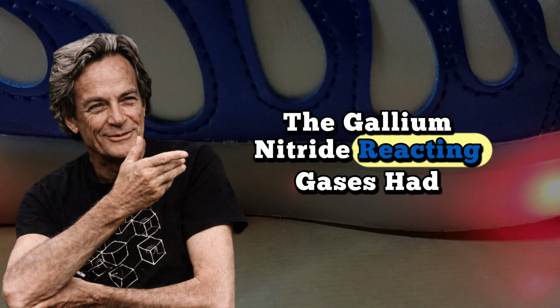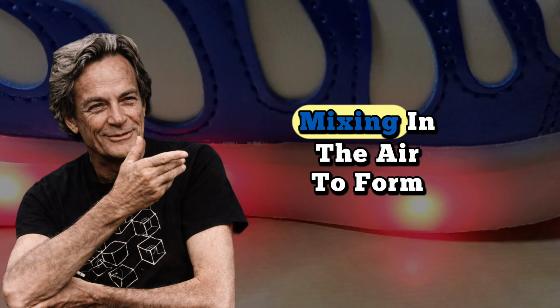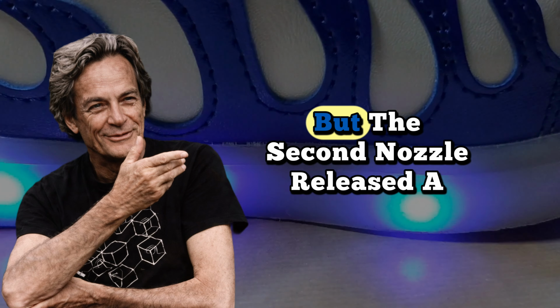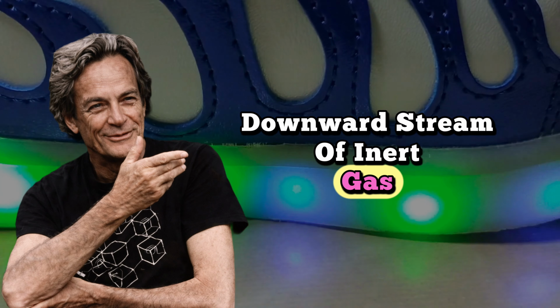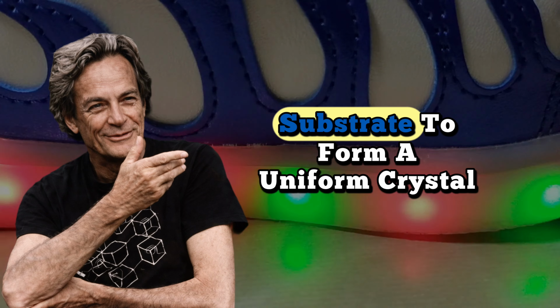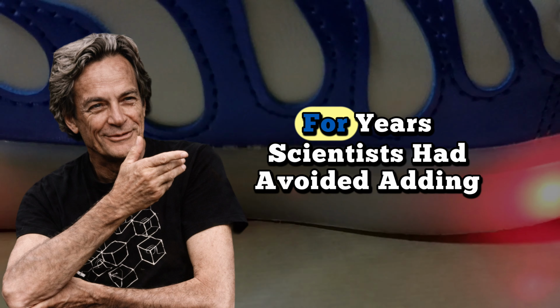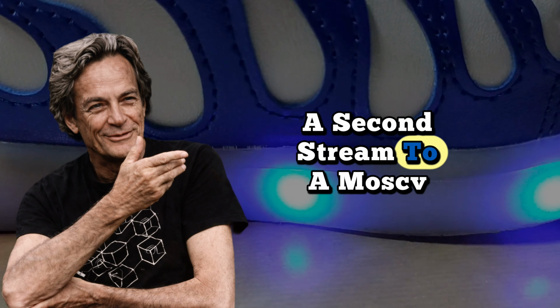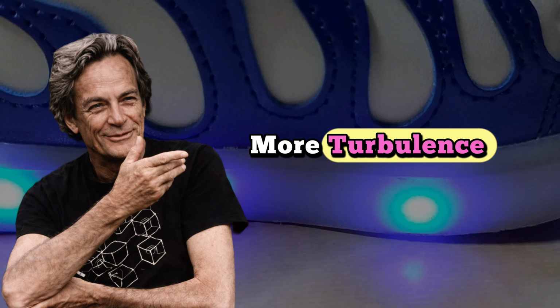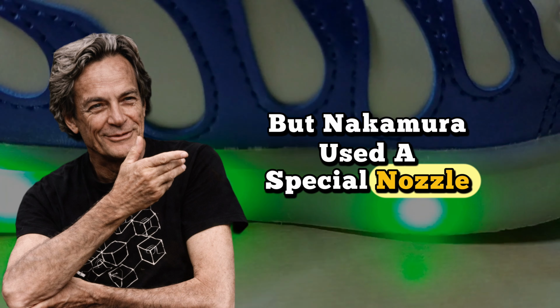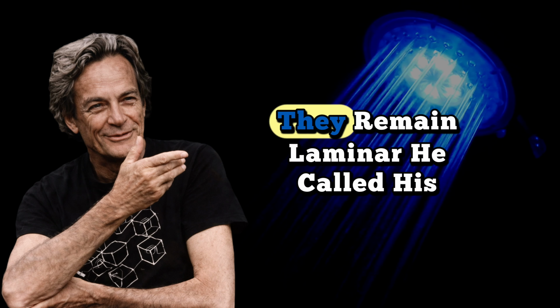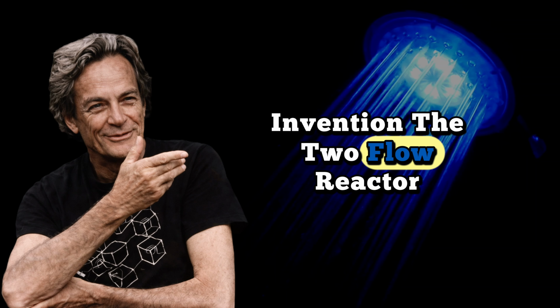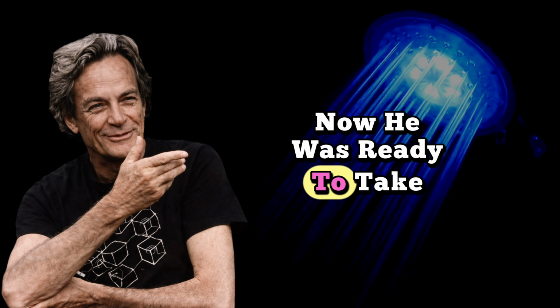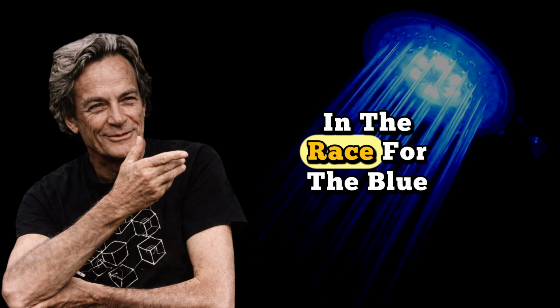The gallium nitride reacting gases had been rising in the hot chamber, mixing in the air to form powdery waste. But the second nozzle released a downward stream of inert gas, pinning the first flow to the substrate to form a uniform crystal. For years, scientists had avoided adding a second stream to MOCVD because they thought it would introduce more turbulence. But Nakamura used a special nozzle so that even when streams combine, they remain laminar. He called his invention the two-flow reactor. Now, he was ready to take on Akasaki and Amano in the race for the blue LED.